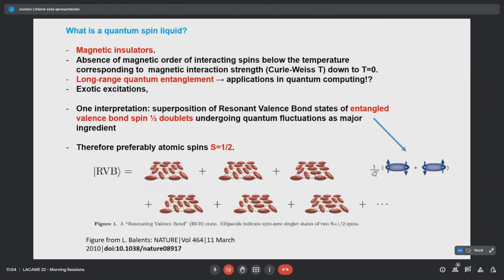There are a lot of exotic excitations you may have in these systems. One interpretation of why the state is formed was proposed: it's coming from a superposition of valence bond states in a resonant way, so-called resonant valence bond states. These are entangled valence bond doublets of spin 1/2, as it is described here, spin up, spin down and spin down, up, that's entangled, but many of them are distributed on, for instance, a frustrated lattice, on a triangular lattice, as you see here.